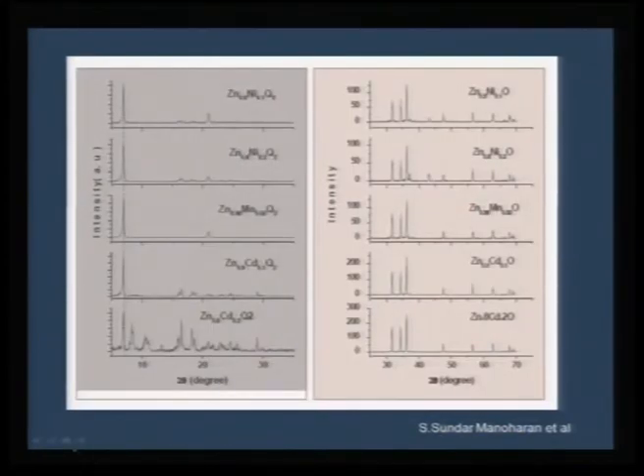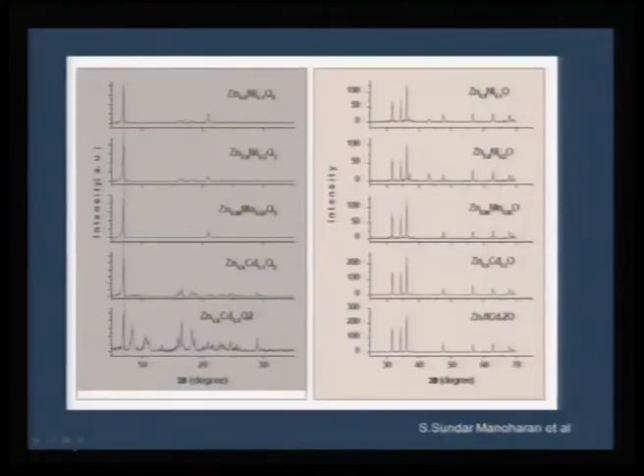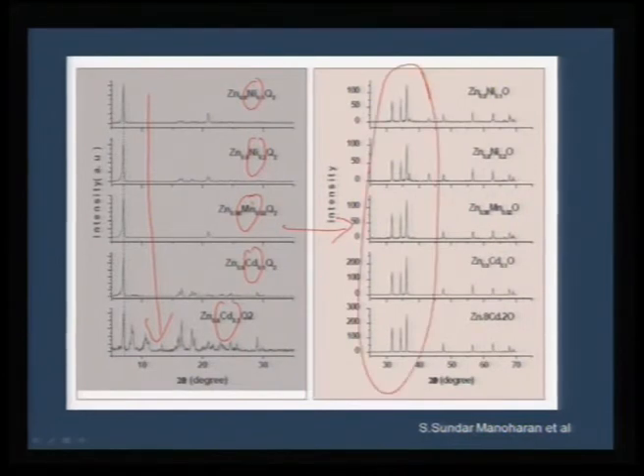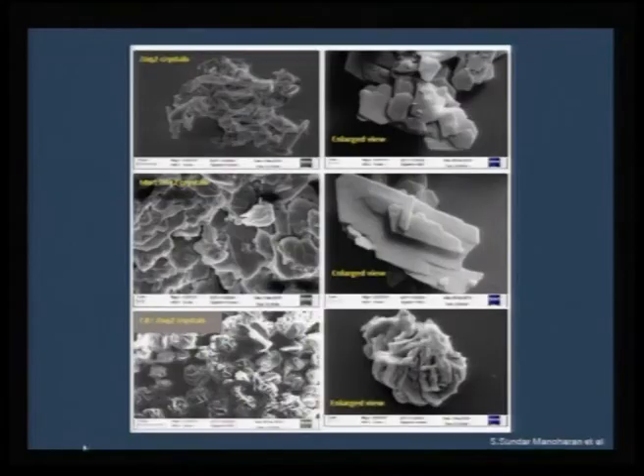Not only can we do this for aluminum, but we can also play around with such precursors for zinc based compounds. For example, if you take zinc quinoline and substitute with any other metal ion, nickel or manganese or cadmium, you can get the precursors which are, as you see from here, all isomorphous. They have the same structural pattern, therefore I can make a solid solution, and correspondingly when I heat it, I am able to get a hexagonal zinc oxide wurtzite phase very clearly formed over a wide substitutional range.